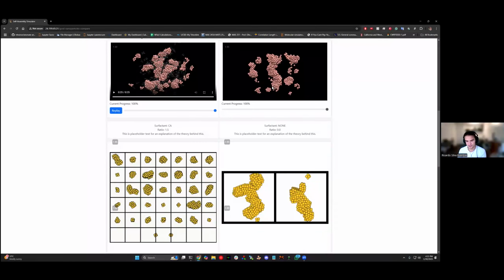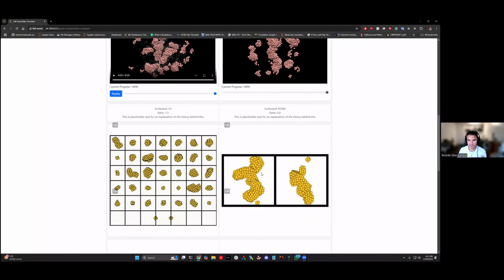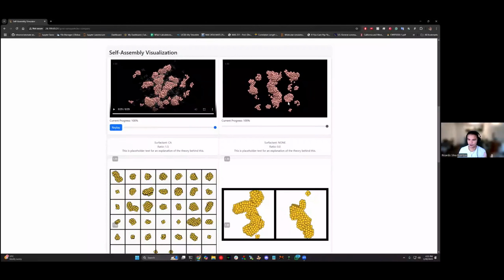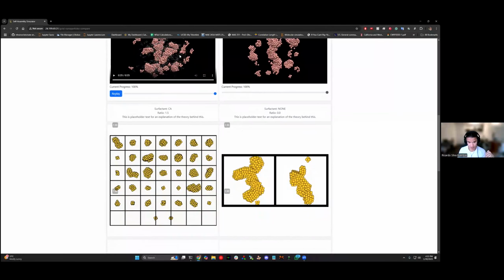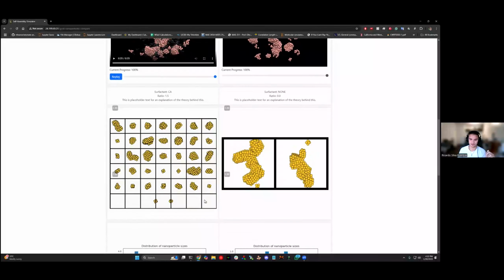10 nanoseconds, I believe. Eventually, all of these gold particles here in solution in water would clump together because they would be vibrating until they find each other. As I mentioned, as if you kept rippling the water in the other example. While here, even if they come closer together throughout the vibrations, the citric acid is blocking these nanoclusters from merging with each other. So you actually get the formation of these nanoparticles here.